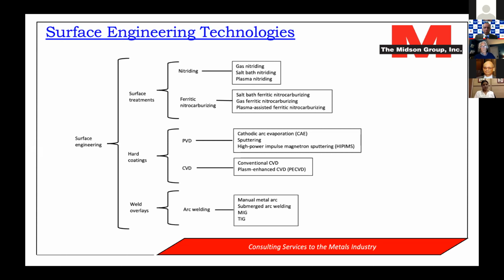Hard coatings are newer, over the last 20 years or so, and basically consist of PVD, physical vapor deposition, and CVD, chemical vapor deposition. CVD is not used a lot in coating dies because normally the substrate temperature has to be raised too high and will soften the die. So PVD is the process that's normally used. Then the third one is weld overlays. Weld overlays, at least in my experience, are not commonly used in die casting, but have been used in the forging industry, where they also use H13 steel dies. So we're not going to be talking about that today. The focus today is going to be on hard coatings, mostly PVD type coatings.